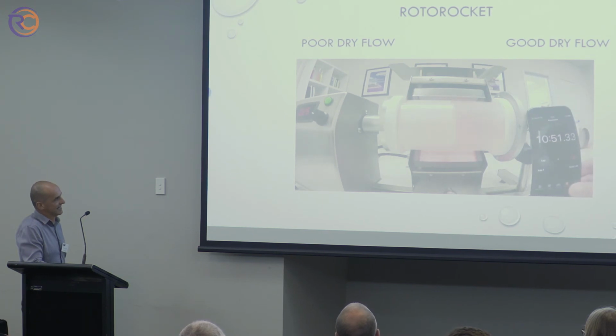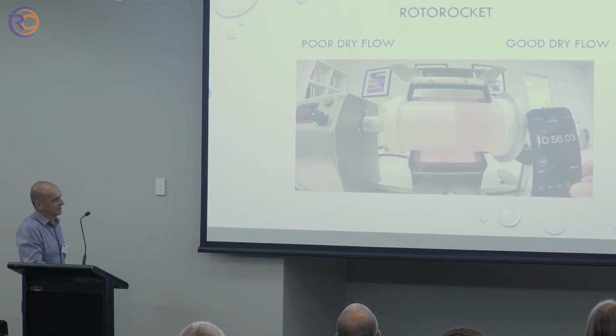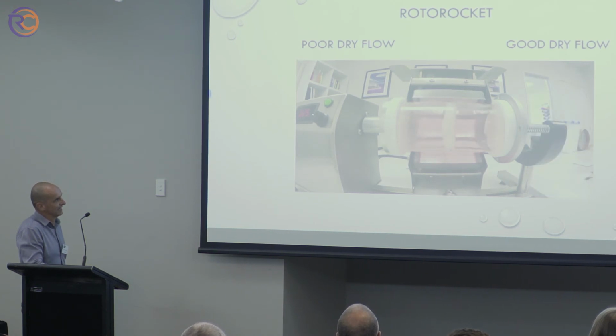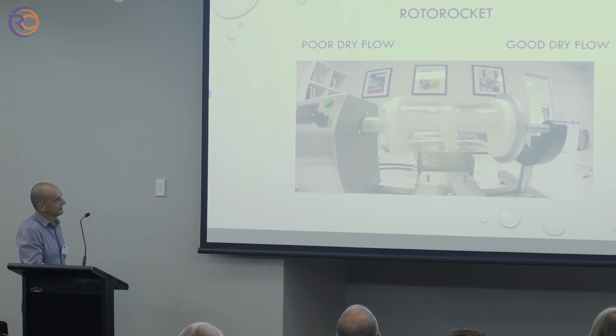And here you can see, at the same time, the bubble dissipation for the good powder: the bubbles are leaving the material a lot quicker than the poorly ground powder. And closer towards the end of the cycle, you can still see the difference. The inside surface here is a little bit rougher, and getting really close to the end now, there's still some residue of not flowing, or the material not melting out. And again, these are the same melt flows, same densities, same batch of raw material.